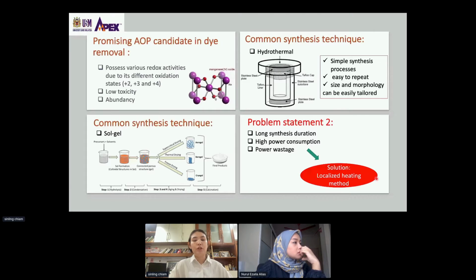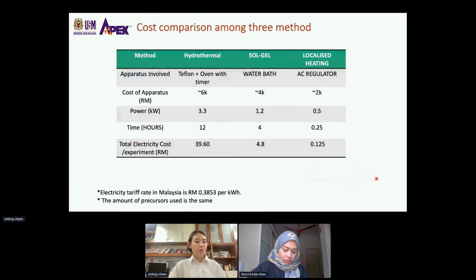In this study, we introduced the use of the localized heating method. It is a rapid synthesis method using the passage of electric current to generate heat and transfer it directly to the target solution. First, we show the price comparison among three methods, which are hydrothermal, sol-gel, and localized heating. As you can see, the cost of apparatus for hydrothermal is around 6,000 Malaysian ringgit, including a Teflon and oven. For sol-gel it is around 4,000 Malaysian ringgit, whereas for localized heating, we only need 2,000 Malaysian ringgit to buy an AC regulator.